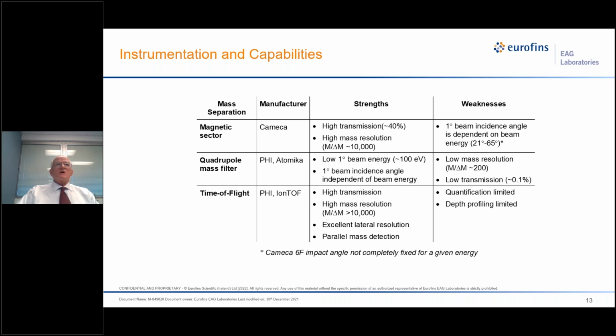Now, these three types of instruments have strengths and weaknesses. The magnetic sector has high transmission and high mass resolution. The high mass resolution allows us to resolve many mass interferences, which are very common in SIMS. But it has a weakness that the primary beam angle, which is fairly important, is dependent on the primary beam energy, and it also is very difficult to bombard with a very low energy ion beam with a magnetic sector.